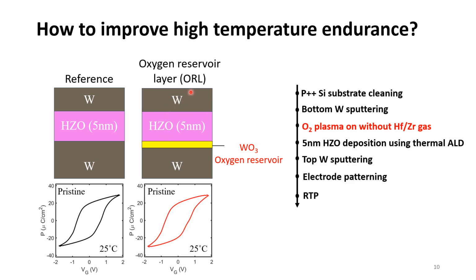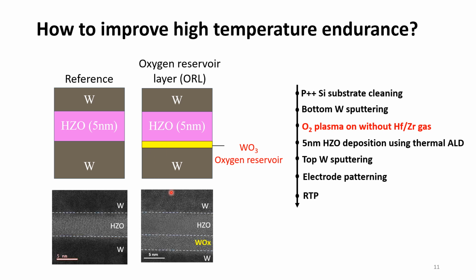Next, we sputter tungsten again of 70 nanometers thickness for the top electrode, and you can see the corresponding PV loops at the bottom. We did the TEM imaging of both the devices. So you can see here in the ORL device, or the oxygen reservoir layer device, we can clearly see the presence of tungsten oxide, which is absent in the reference device. Going forward in my talk, I will be referring to this device, which has oxygen reservoir layer or tungsten oxide, as the ORL device.